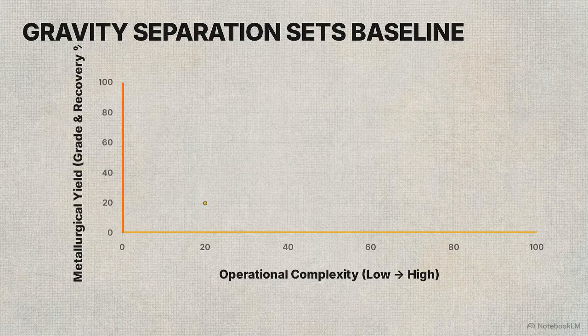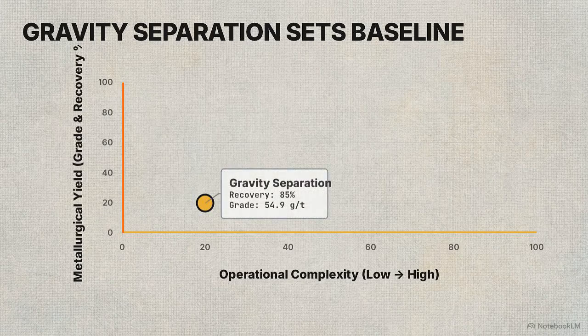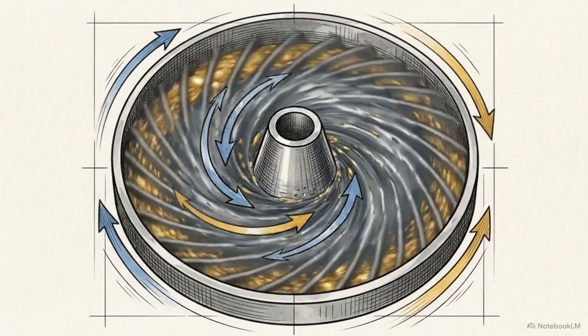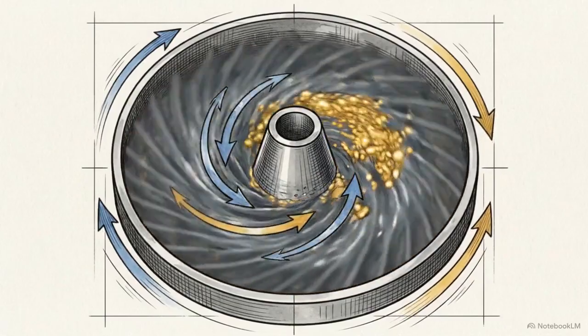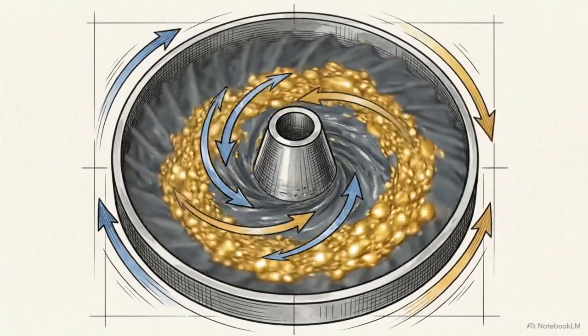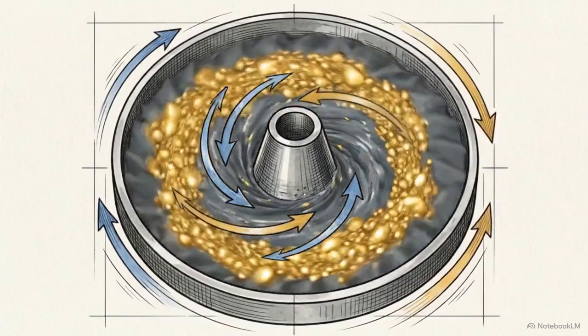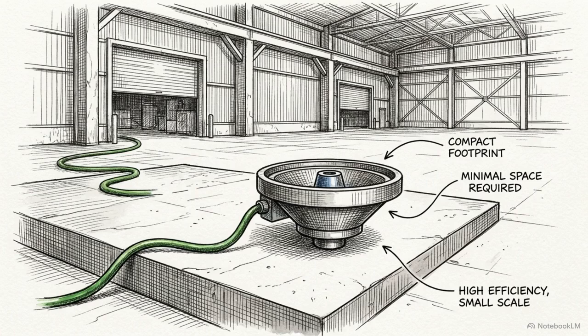In the lower left quadrant, gravity separation serves as the baseline. It provides an 85% recovery rate and a 54.9 gram per ton grade. This method uses a centrifugal concentrator to spin the crushed material, which separates heavier gold particles and removes the waste slime. It requires very little energy to operate and occupies a small physical footprint on the site.